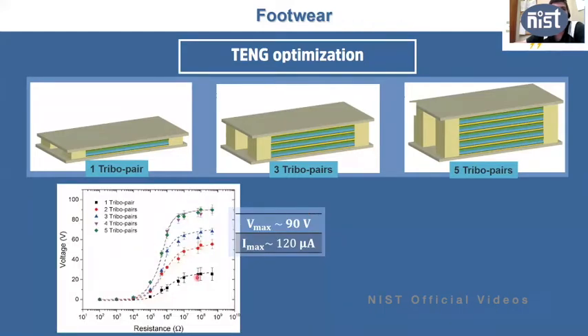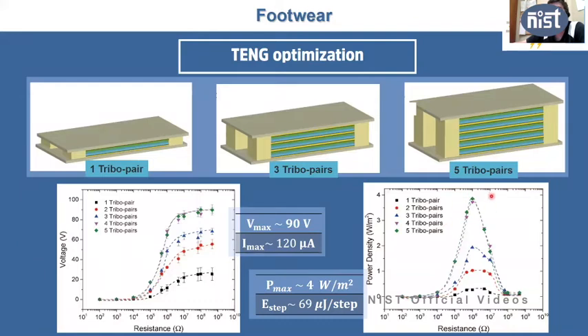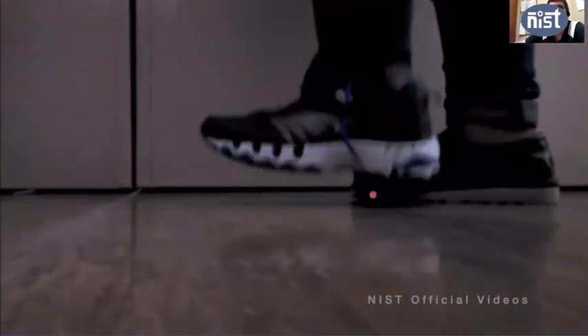If you increase the number of pairs from 1 to 4, you increase continuously the output power that you get, and you go up to 90 volts and 120 microamps of current. But after a given value, in this case 4 tribo pairs, the output doesn't increase more because the pressure that you put on the structure is not enough to make all of it come into contact. This is the power. It confirms what I'm saying. The maximum power is 4 watts per square meter, and you have it for 4 and 5 pairs of this configuration. This is how it looks. You have someone stepping on the floor, and you have these 3 LEDs that are being lit by the triboelectric generator that is inside.